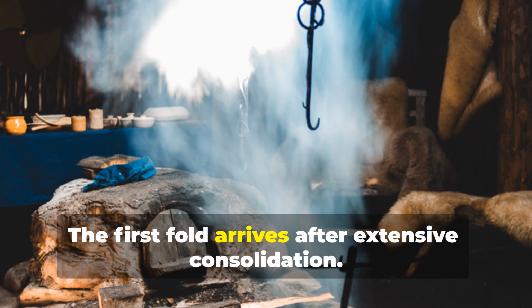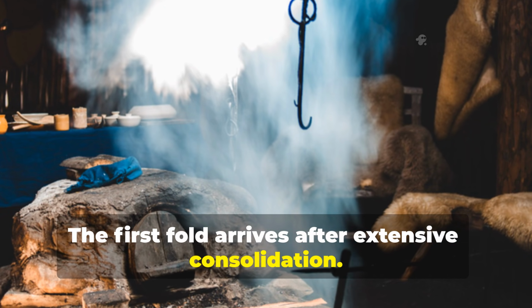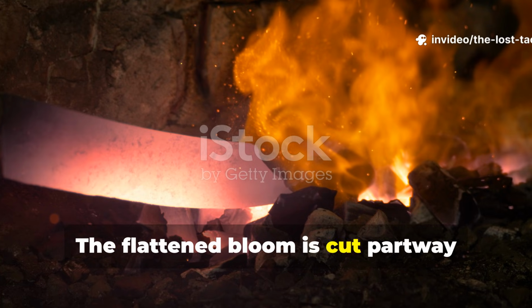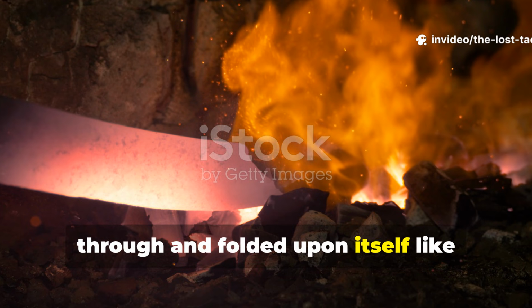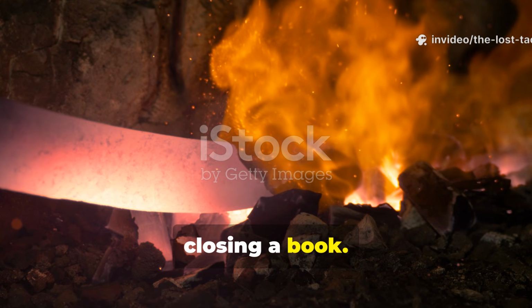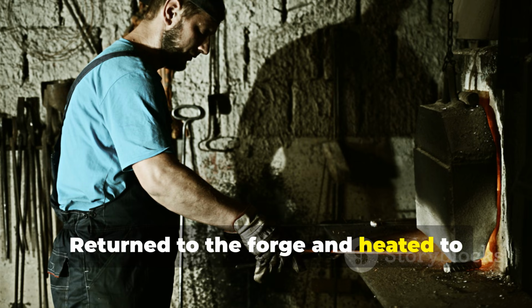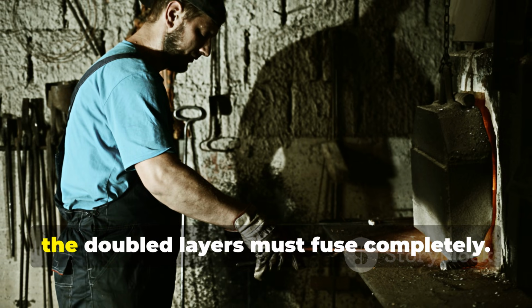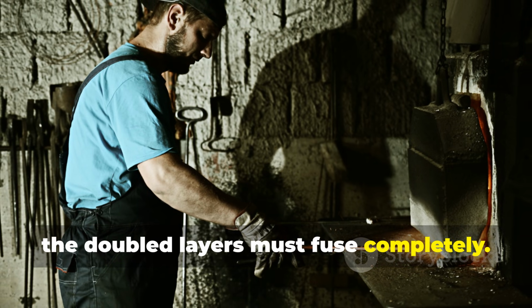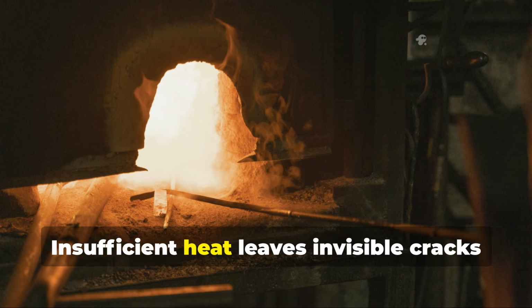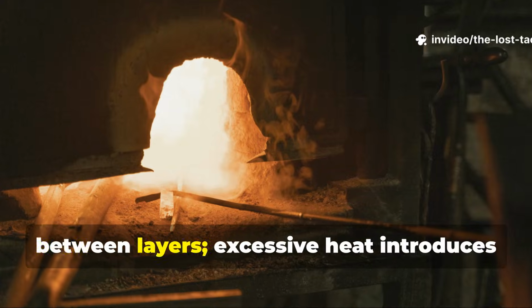The first fold arrives after extensive consolidation. The flattened bloom is cut partway through and folded upon itself like closing a book. Returned to the forge and heated to welding temperature, the doubled layers must fuse completely. Insufficient heat leaves invisible cracks between layers.